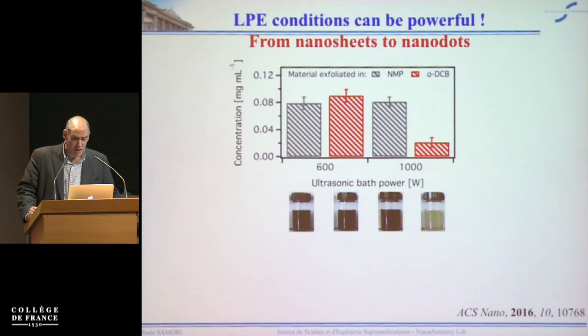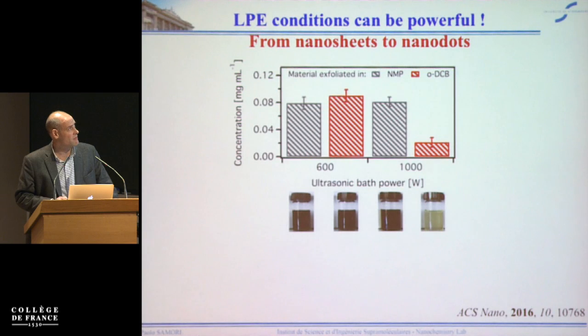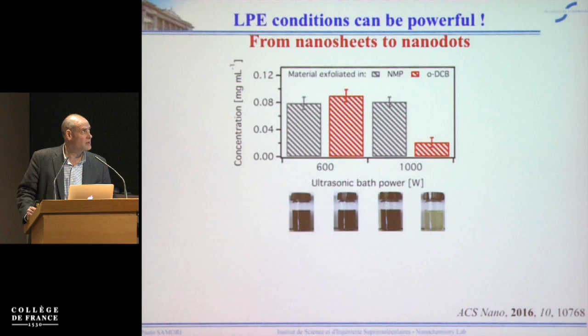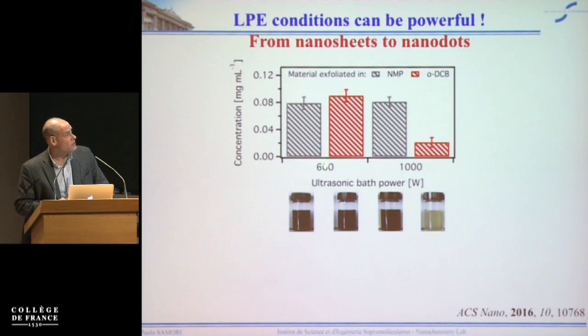Now, going back one step, you can do exfoliation also without molecules. You can just do this with a given solvent. You can use NMP or another good solvent for doing the exfoliation by sonication, such as dichlorobenzene. Now, we found something that was unexpected: you can play with the power of your bath sonicator. With NMP there is no major change when it goes from 600 to 1000 watt, whereas we found a major change when we increased the power of sonication from 600 to 1000 watt using dichlorobenzene.